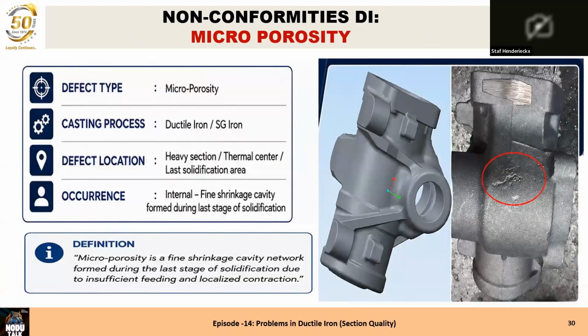Microporosity is very typical for ductile iron castings. It appears in heavy sections, in the thermal center, and the last solidification area. That's very, very important: microporosity always happens in the last solidification area. And it's very difficult to compensate because it's in the area where it appears. At the end there was some shrinkage and the riser could not reach it anymore because there was no feeding possibility anymore, and it will be very small defects coming very close to one another, and it can't be found by ultrasonic very, very easily. So it's the most difficult defect or porosity that appears with ductile iron.